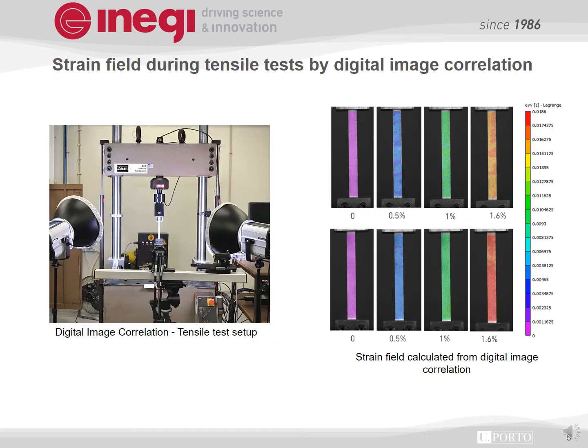Strain field during tensile test by digital image correlation. Image on the left side of the screen shows the digital image correlation test setup. On the right hand side shows the strain field calculated by using the VIC-2D software. It used the Lagrange strain for calculating the strain field. The graph above shows the reference specimen strain field, and graph below shows the electrically conductive test specimen strain field.